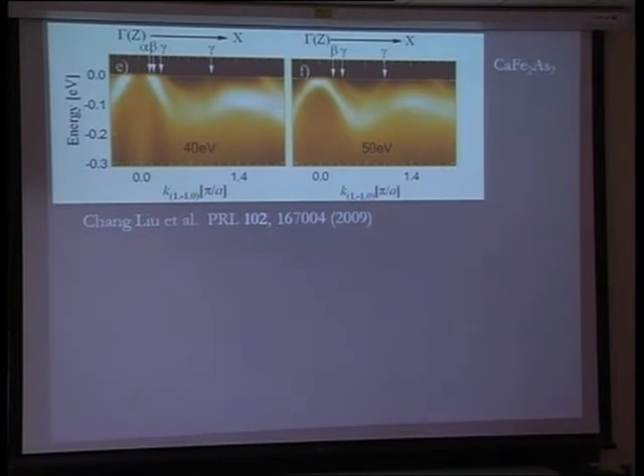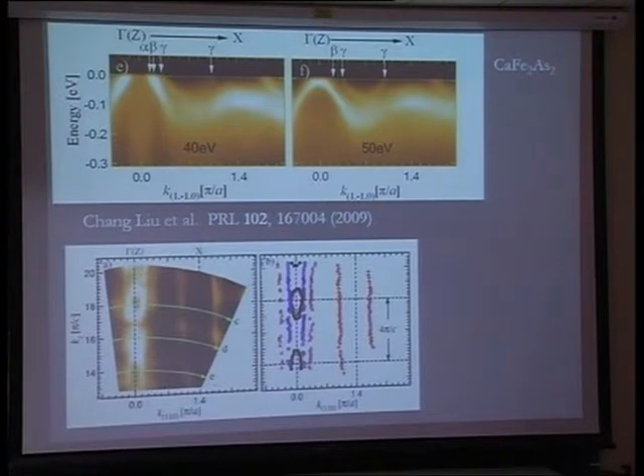So the Fermi surface is supposed to be like 2D, and 2D means it's a cylindrical kind of Fermi surface. So if you change kz vector, it shouldn't vary. You should see a similar kind of Fermi surface, but here it varies with kz. So the whole Fermi surface which has been mapped here shows a kind of cylindrical structure, which has been schematically shown here, the same band structure around the gamma point, but you can see that some of the bands show some kind of deviation from the 2D kind of structure, which are these black ones. So the alpha band somehow deviates from this effective 2D kind of structure.